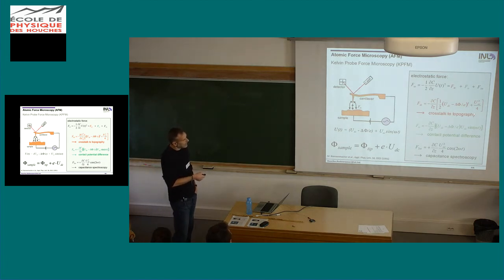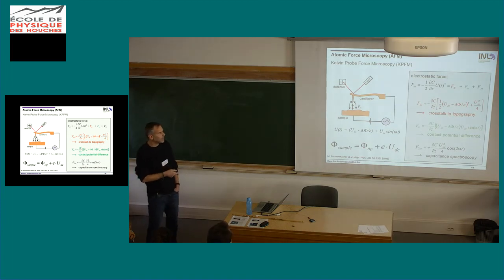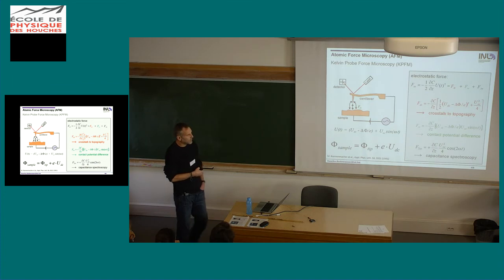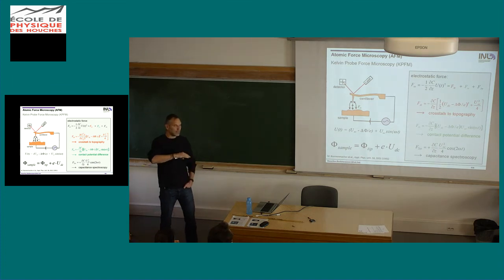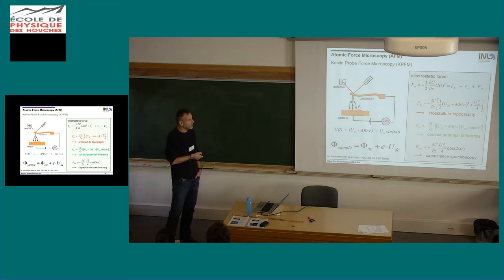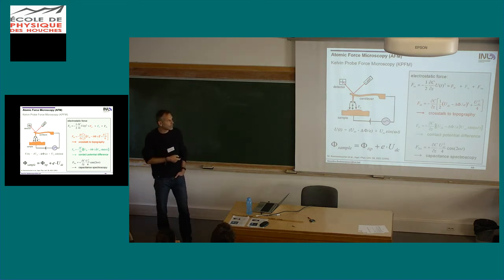So the DC part actually contributes to the topography. So this is an addition to the topography. And then what's important for Kelvin probe force microscopy is this force at the frequency of the AC bias. So what we do is we apply the AC bias, and then this AC bias will induce an oscillation because there's a force that's written here of the cantilever at this additional frequency that we apply here. It's an electrostatically induced oscillation. And of course we can detect this with our laser system here. So we just take the signal from the photodiode, feed it into a lock-in amplifier that is tuned to that frequency, and we get the amplitude of oscillation at this frequency. And of course that's proportional to the force at this one.